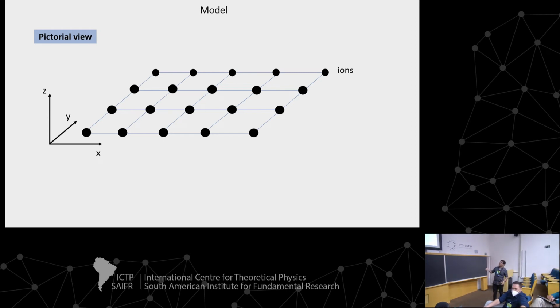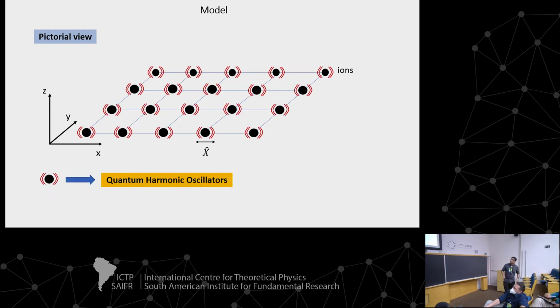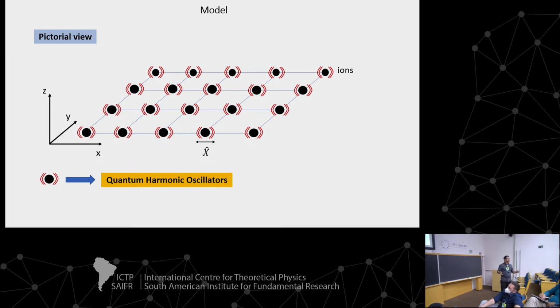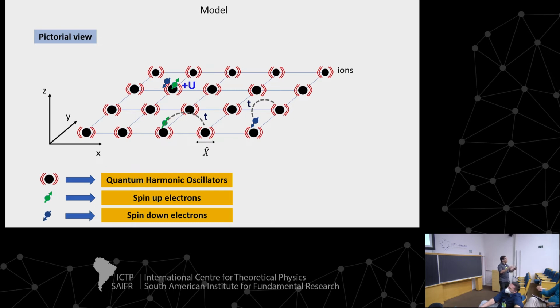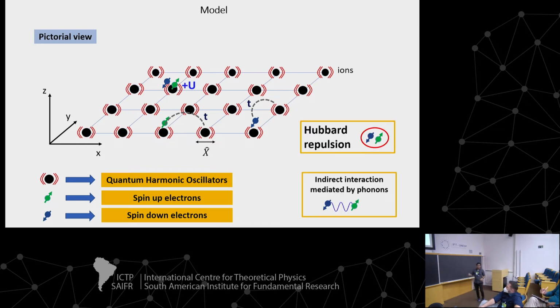So we have a lattice, so this is a pictorial view, on which I will put phonons. The phonons to me are basically harmonic oscillators that are vibrating in my lattice. And I have also electrons. These electrons can hop from one site to the other. And these electrons also interact when they are local, playing the role of the Coulomb interactions. So here we have the Hubbard interaction. You also have the electron-phonon interactions because of the harmonic oscillators that we have on each site.